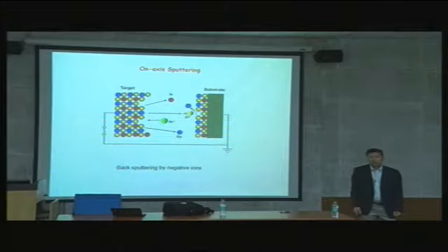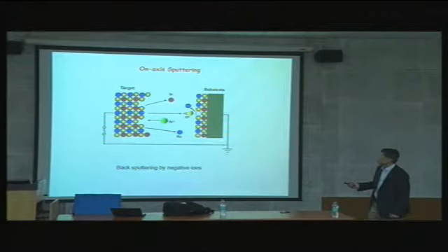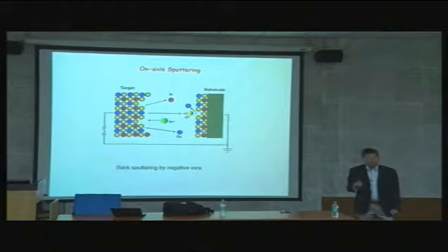But a lot of people initially didn't realize what the serious problem of this sputtering was. And the problem is when you sputter, not just this metal, strontium and ruthenium, is either neutral or ions. You can have both come out. Okay? Because when you sputter, when you break the bond, it can be ions or it can be neutral. And the ions can be easily combined with electrons and become neutral.